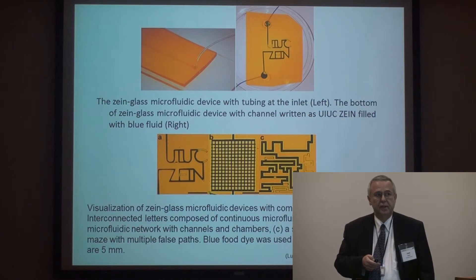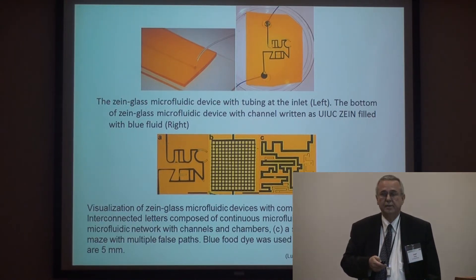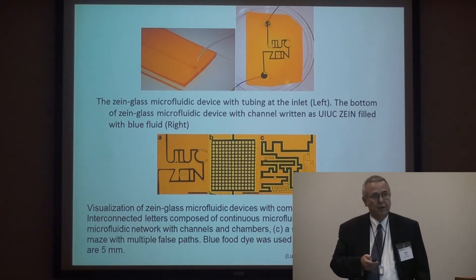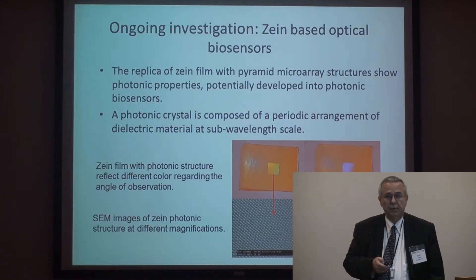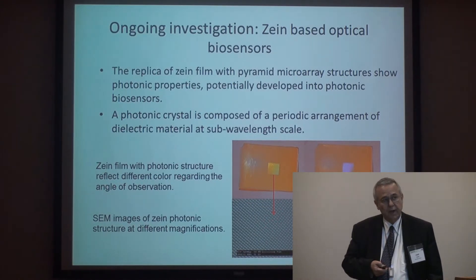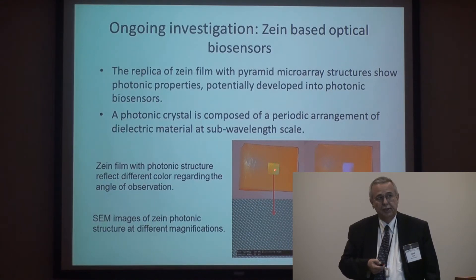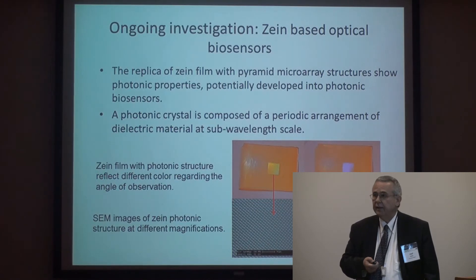We're very much interested in utilizing this platform for different applications. A couple of areas we are starting with include RNA and DNA extraction using these microfluidic devices. Another area we have been focusing on is creating photonic properties on Zein. Depending on the type of surface we're able to create — this is really Dr. Lu's expertise — we can actually alter the color of Zein. With pyramid-shaped nano-sized structures, we are able to create yellowish-green colors, and by reducing the size considerably, we can make Zein purple. This leads to the development of sensors utilizing these biodegradable materials.